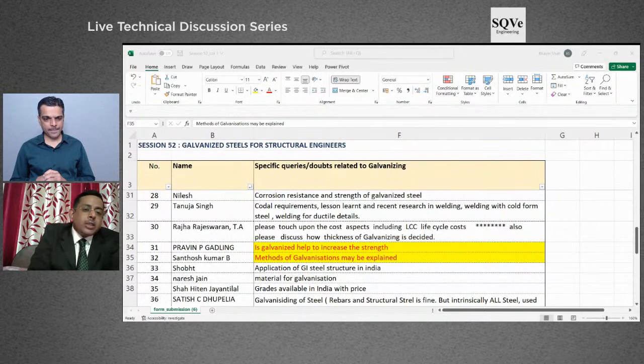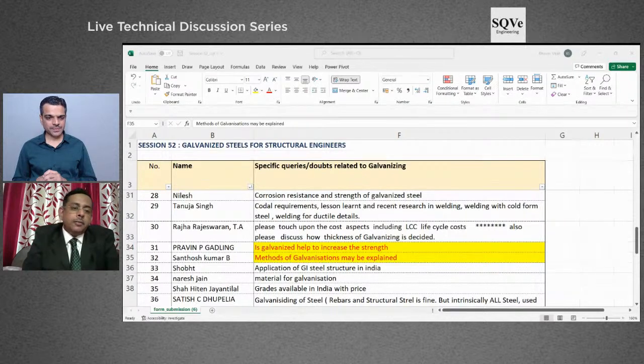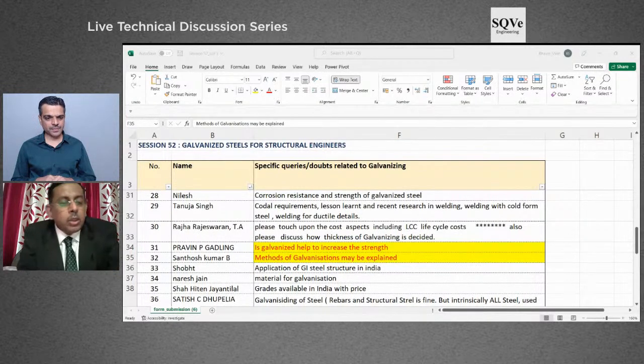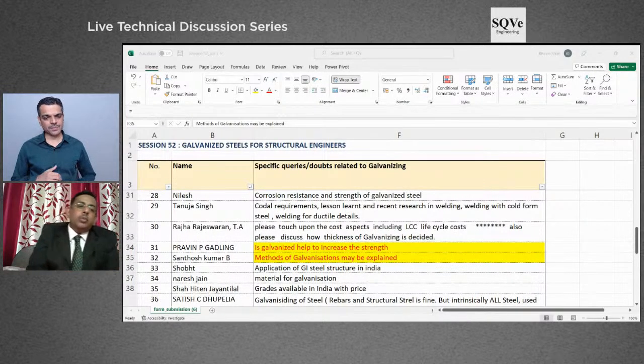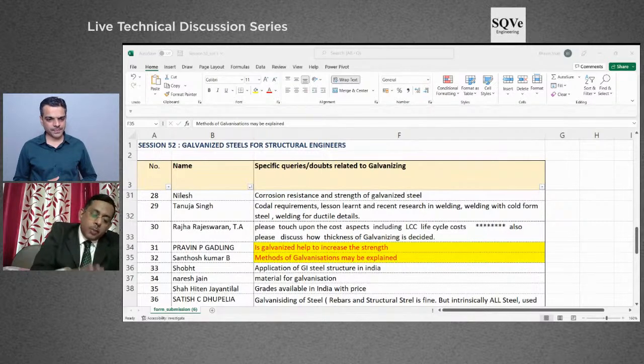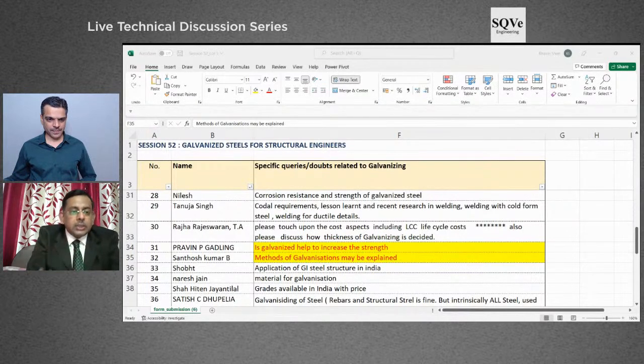In the case of batch galvanizing, once you have the component, it has to be cleaned properly with a degreasing or maybe acid degreasing process. You need to clean that. After that, you need to put some flux. Flux is an agent which makes a bond between the steel surface and the zinc. So you put the flux, and with the flux coated, samples are dipped inside the liquid bath for some time.